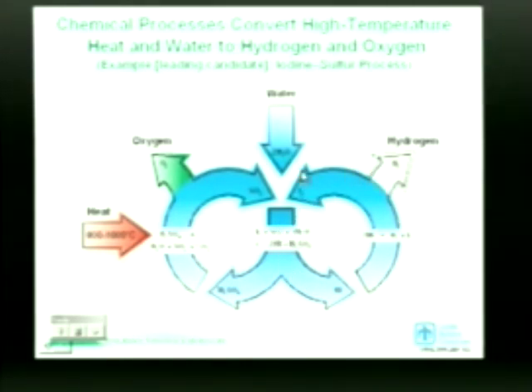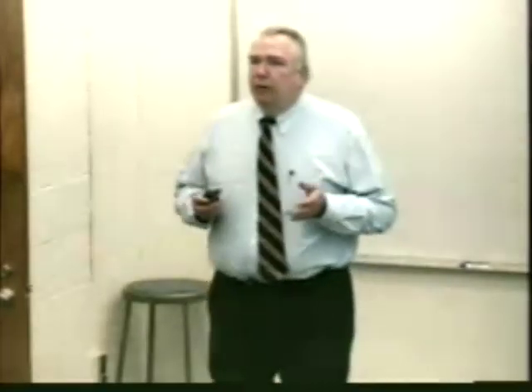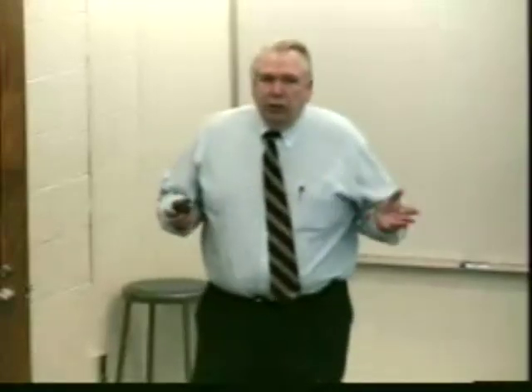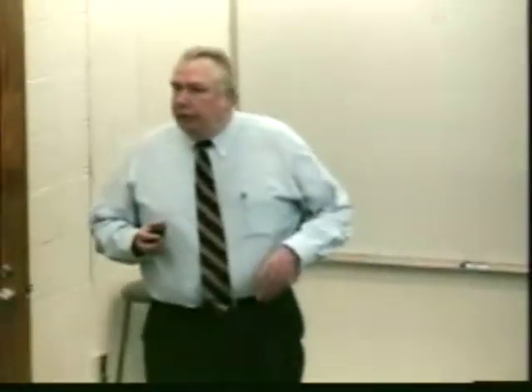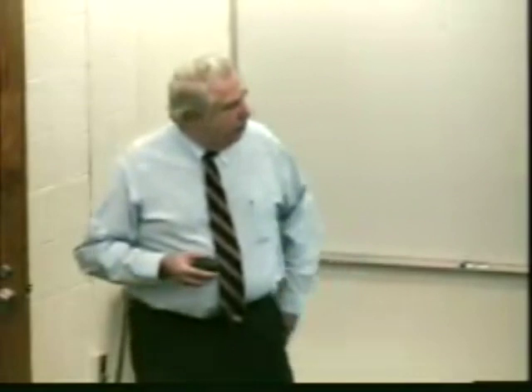So we have two coupled chemical reactions with a net result of heat plus water equals hydrogen plus oxygen. The catch is that this reaction is a high-temperature dissociation reaction where the heat has to be provided all at high temperature. It does no good to provide heat at 700 degrees Celsius. Worthless for this process.